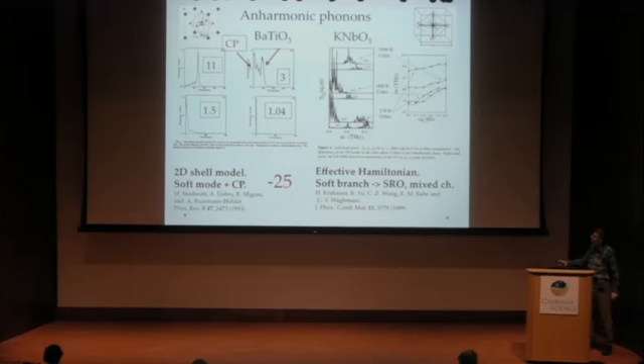Now, about the same time as the first principles calculations appeared, there was also a question: what happens with the unstable mode at high temperatures? And these are the simulations at finite temperatures, which show us the spectrum. This is at 11 times Tc, 3 times Tc, 1.5 Tc, and almost above Tc. What is the dynamical structure factor? This is the frequency and intensity, and we see the soft mode in the barium titanate model, which was described by a two-dimensional shell model at that time.